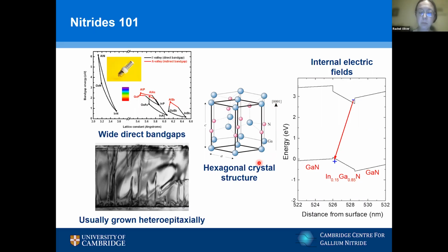That polarization, and also the fact the material is highly piezoelectric, means that when we grow structures like here, an indium gallium nitride quantum well, where the indium gallium nitride will be in compression, internal fields arise from the polarization, strain related and spontaneous, within the crystal structure. And those internal fields tend to separate electrons and holes, driving them to opposite sides of here, a quantum well, but could equally be a quantum dot.